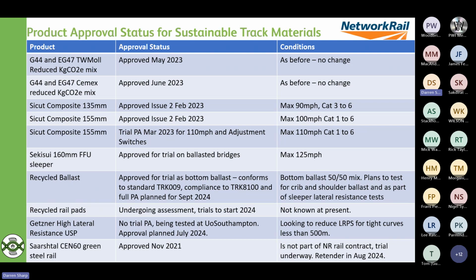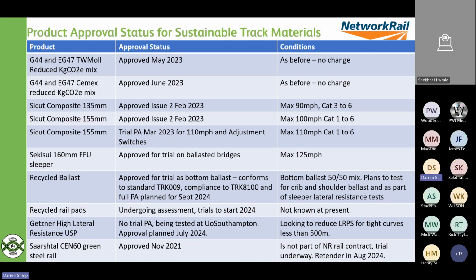And we've got a new low carbon mix, and they were approved earlier this year, May and June. That's reducing the carbon by between 40 to 50%, 30 to 40%. So that for us was a big win. The Sicut Composite sleepers, again, reminding people that they've been approved since February 23 for issue 2, and we also have trial product acceptance for March 23 for 110 mile/hour sites, and also for use on adjustment switches.